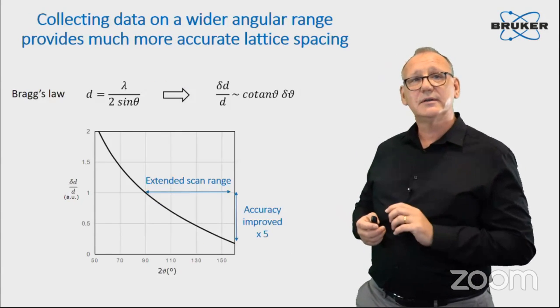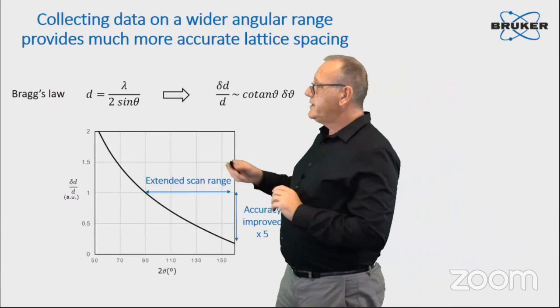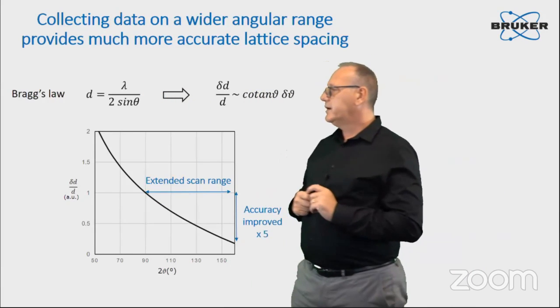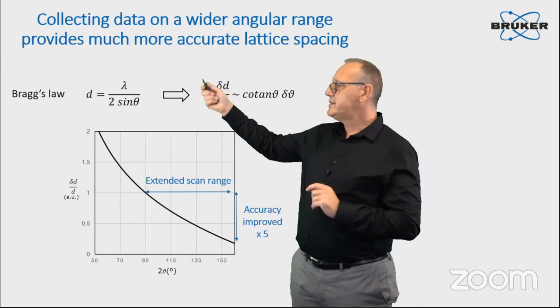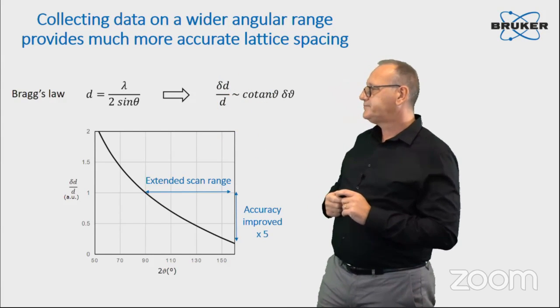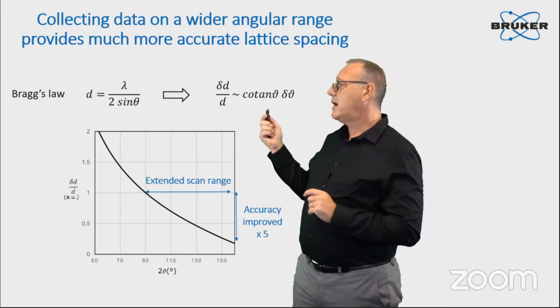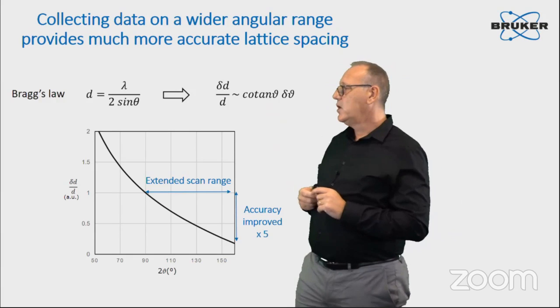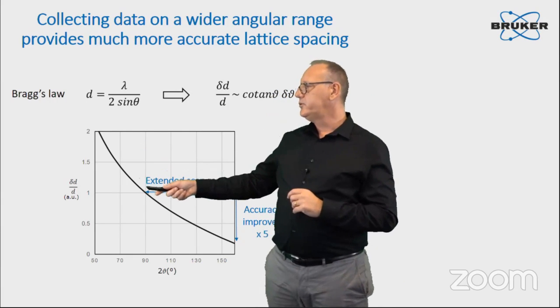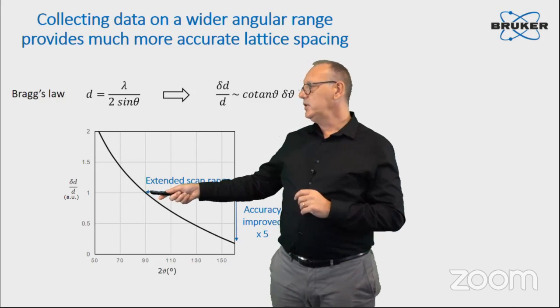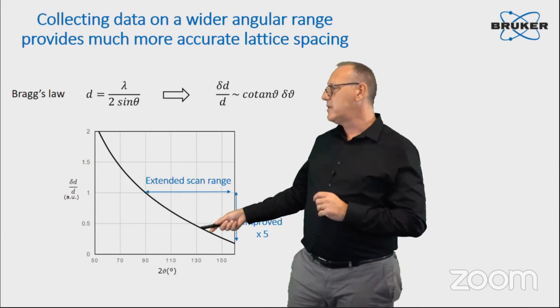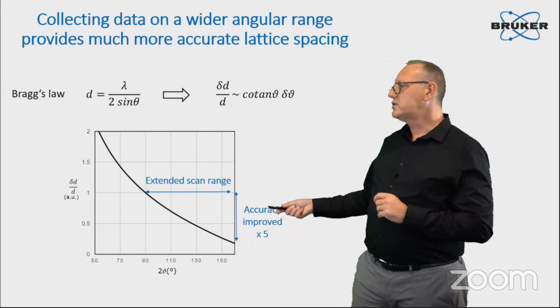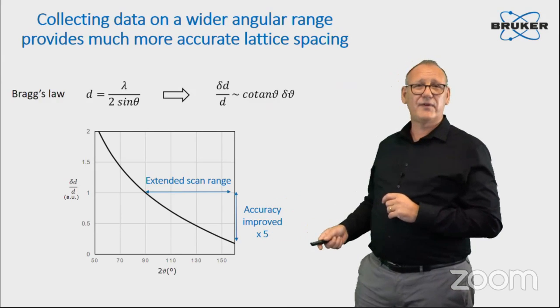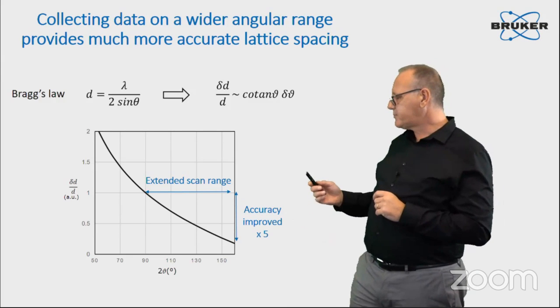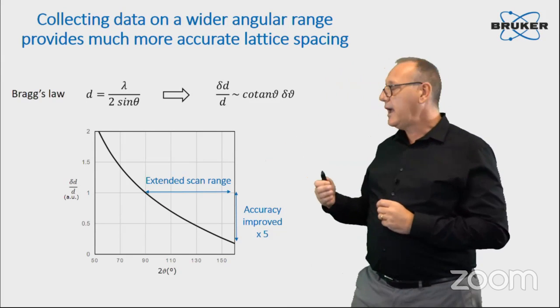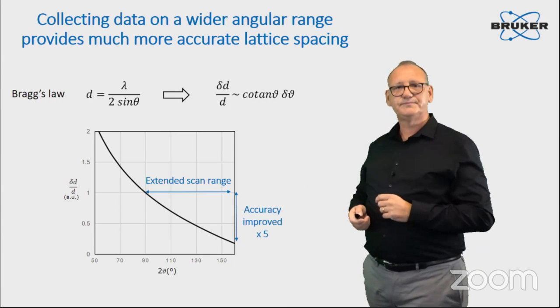Even if you have no stress, if we consider our Bragg law here, and you make a differentiation to estimate the relative error versus the maximum scanning range you have achieved, you find that if you measure up to 90 degrees, you end up with this kind of accuracy. But if you extend it up to the maximum accessible range, you will actually improve your lattice parameter determination by a factor of 5. So I think it's probably worth spending another hour and make sure you can have even more accurate results.